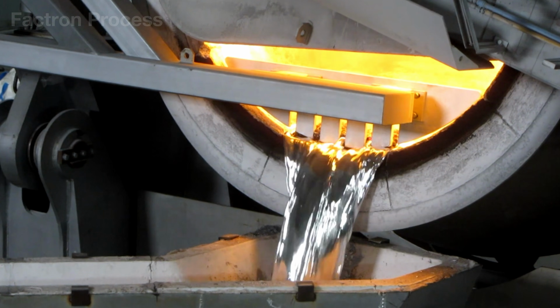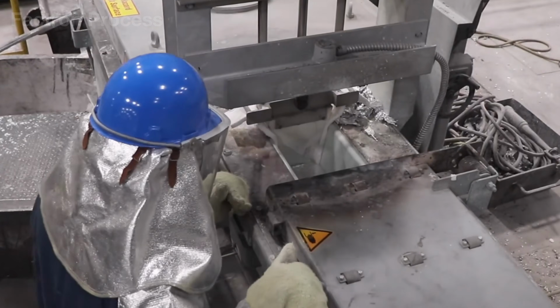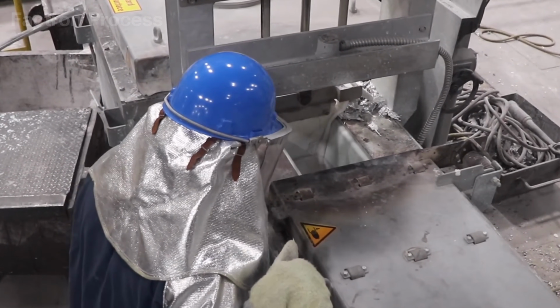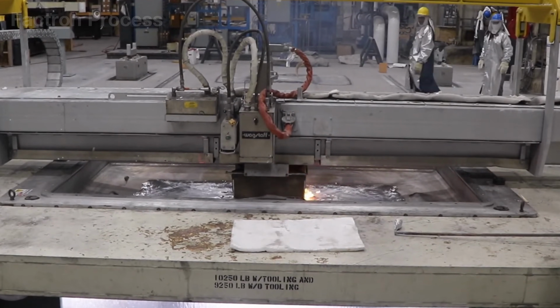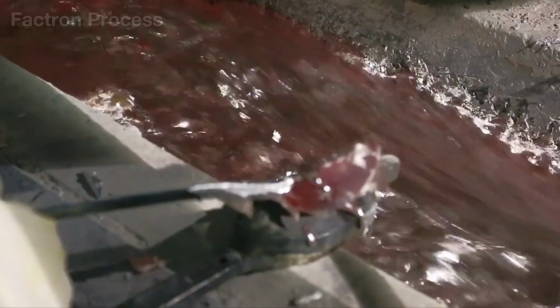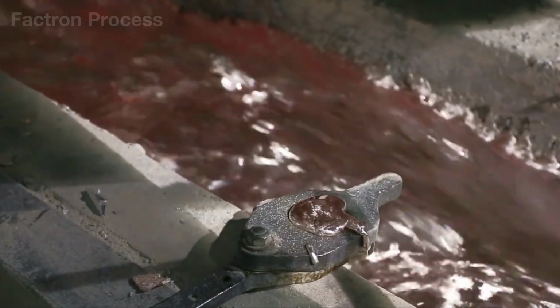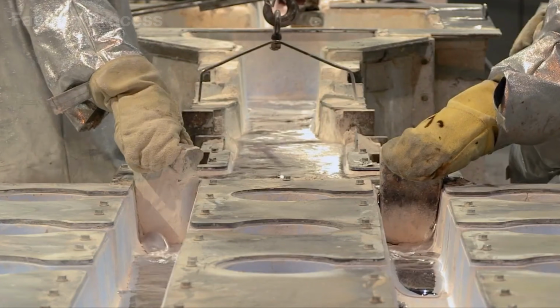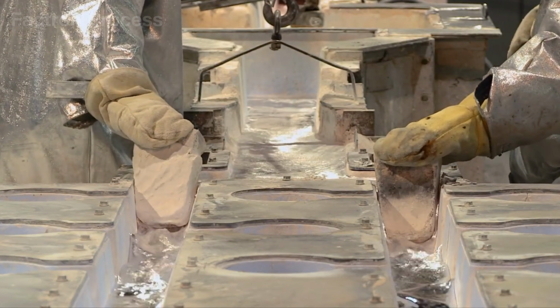After approximately 2.5 hours, the final portion of molten aluminum has completely solidified. A gigantic slab ingot, nearly 10 meters long and weighing around 27 tons, is lifted from the pit. A single block containing roughly as much aluminum as 1.5 million beverage cans.